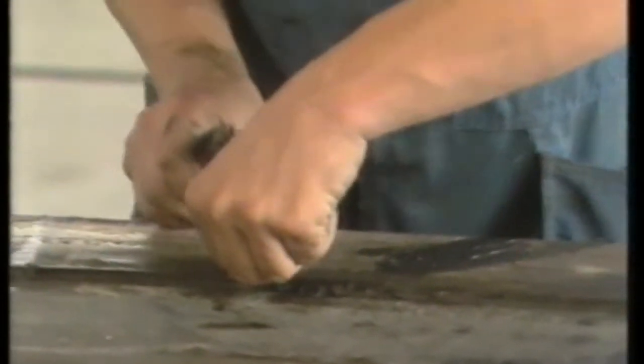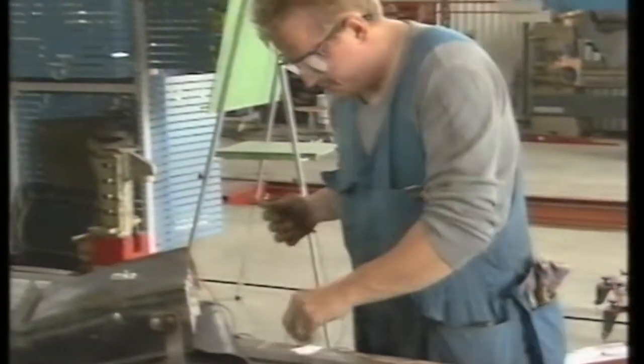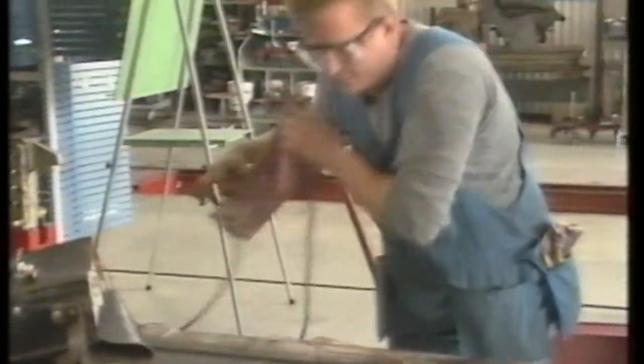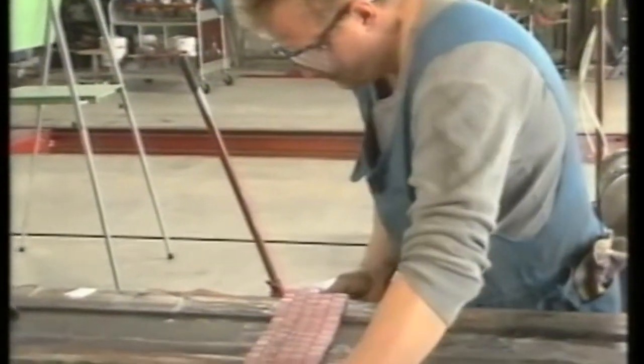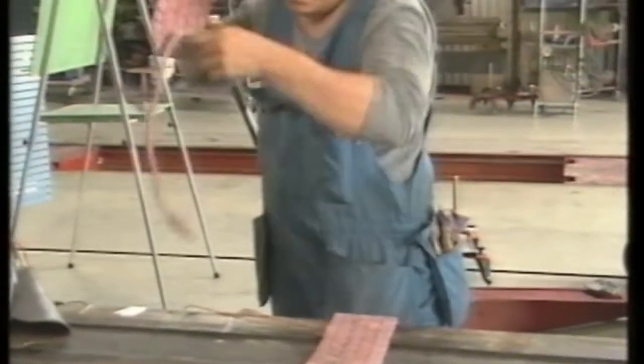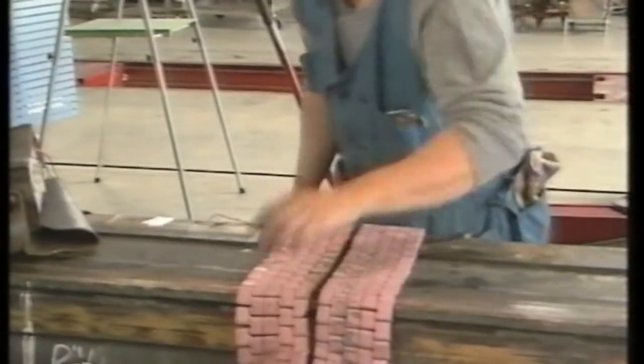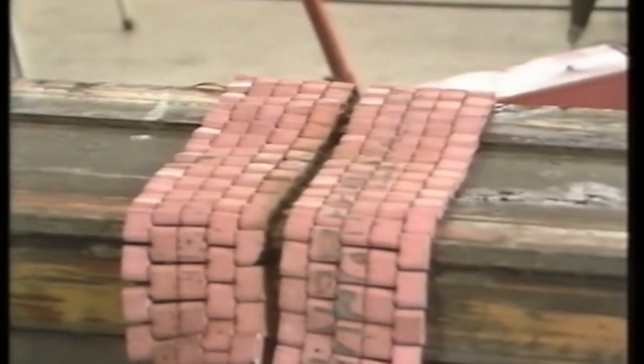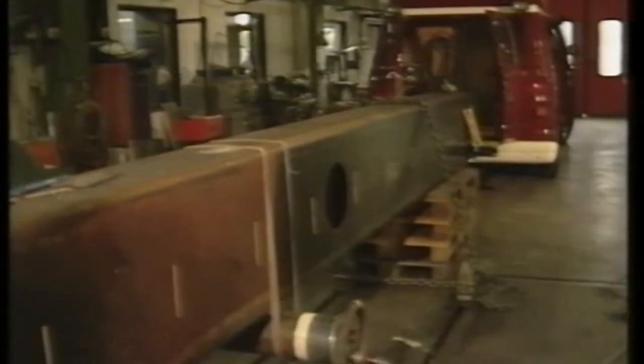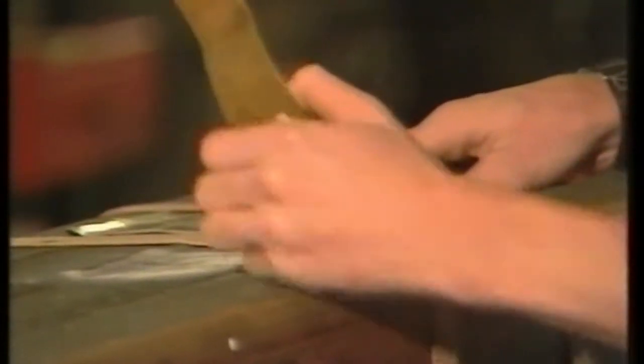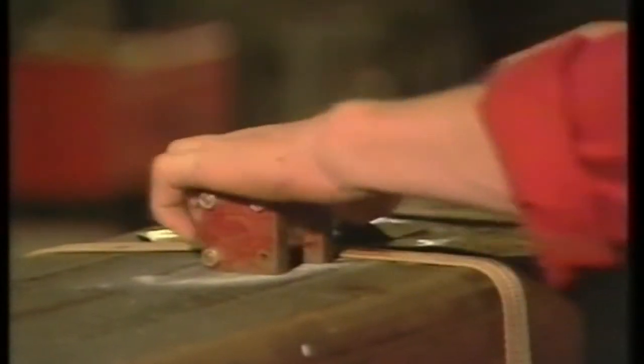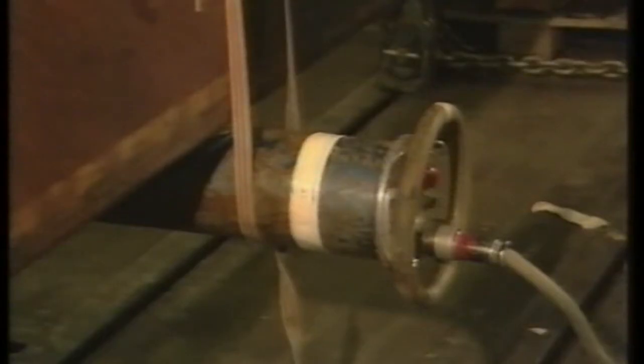Stress-relieving anneal is performed on a few parts after alignment or welding. It is important that heating speed, temperature interval, and holding time have the right values. Careful tests must be done after repairs. Magnetic tests, ultrasound, or as we do here, X-ray. Here we have an X-ray photo that must be examined and graded so that welding can be approved.